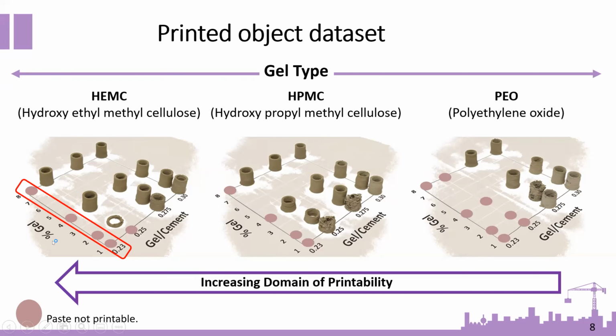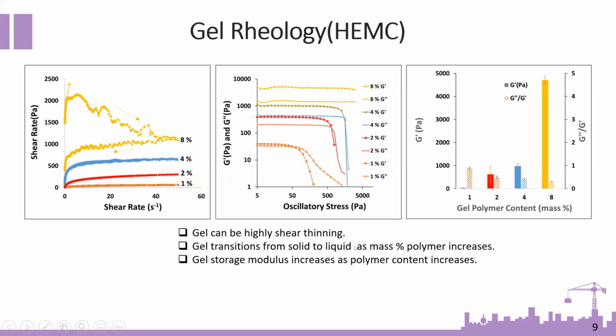We can clearly see that we have domains of unprintable materials, where the material simply didn't come out of the nozzle. We also have domains of very well printed objects and domains of poorly printable materials. So in order to understand why some of these behaviors happen, we performed gel and paste rheology.